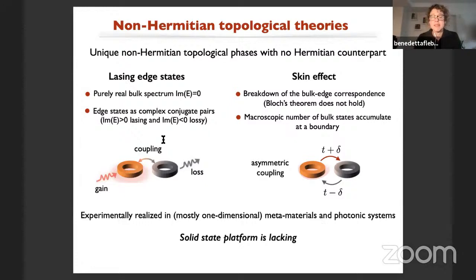So you can engineer these lasing edge states by having a system with a unit cell that contains 2 sites, and judiciously tuning the gain and loss between these 2 sites. On the other side, the skin effect can be easily understood only in 1 dimension in the context of a model in which there is an asymmetric coupling. So this asymmetric coupling is breaking the hermeticity of the model, and it's telling you that it's more convenient for a wave function to go right instead of left, or vice versa. And in these terms, it's kind of easy to see why a bulk wave function will accumulate on one side or another.